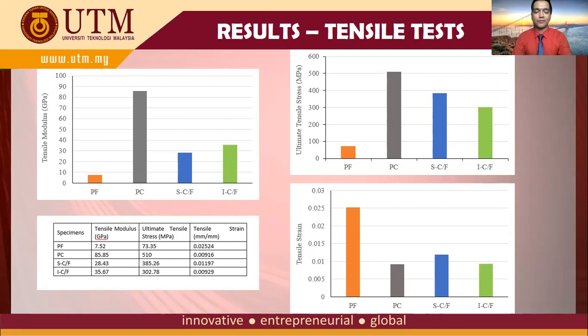For tensile strain, as expected, pure flax has the highest strain because it is a ductile material, and the lowest one is pure carbon because it is a brittle material. So when we combine these materials, we can improve the tensile strain. In particular, when we hybrid flax and carbon with sandwich stacking sequence, it gives better ultimate tensile stress, whereas when we hybrid with intercalation stacking sequence, it gives better tensile modulus. Based on the design requirements for each future product, we can choose either sandwich-like or intercalation stacking sequence.